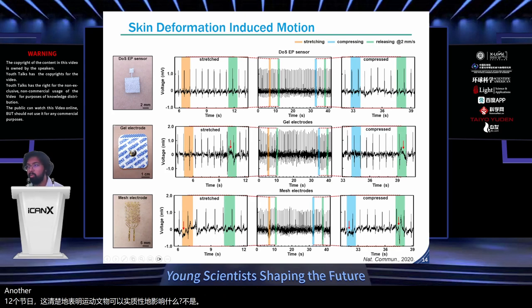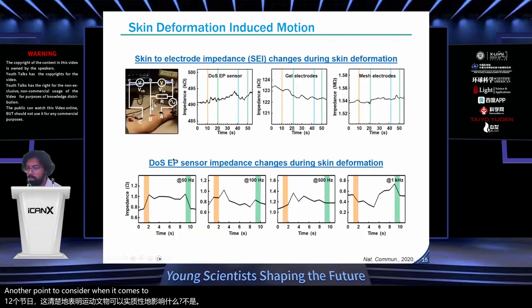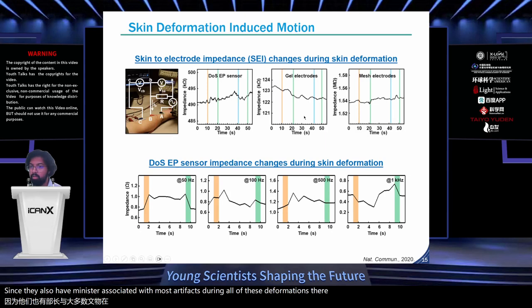Another point to consider when it comes to skin deformation induced motion at the electrode site is a potential change in electrode impedance, since changes have also been associated with artifacts. During all of these deformations, there was no statistically significant difference in the average change of skin-to-electrode impedance between the DOS-EP sensors and the gel electrodes. These data indicate that the change in skin-to-electrode impedance was not a contributor to the artifacts.